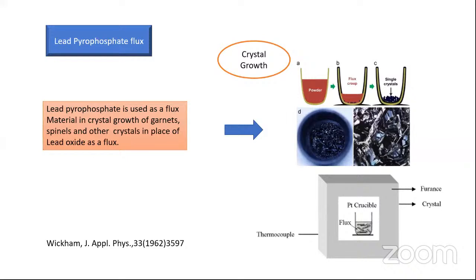Lead pyrophosphate flux. Now, this is another novel application of a pyrophosphate. So, lead pyrophosphate is used as a flux material for growing crystals. Now, many times the crystals are grown by solution method, melt method, and different techniques. For a layman, if we want to grow crystals of sodium chloride from solution, we take sodium chloride and dissolve it in water. When we make a saturated solution, no more sodium chloride dissolves in water. Then we allow it to evaporate. And after evaporation of water, beautiful sodium chloride crystals are grown.